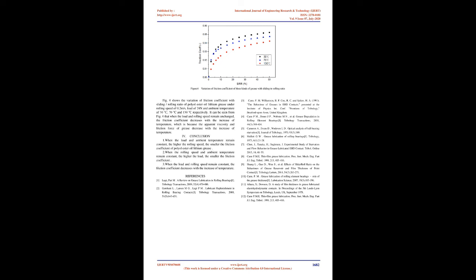Figure 4. Variation of friction coefficient of 3 kinds of grease with sliding to rolling ratio. Fig 4 shows the variation of friction coefficient with sliding/rolling ratio of polyol ester oil lithium grease under rolling speed of 0.2 m/s, load of 24 N and ambient temperature of 30, 70, and 130, respectively. It can be seen from Fig 4 that when the load and rolling speed remain unchanged, the friction coefficient decreases with the increase of temperature, which is because the apparent viscosity and friction force of grease decrease with the increase of temperature. For conclusion: